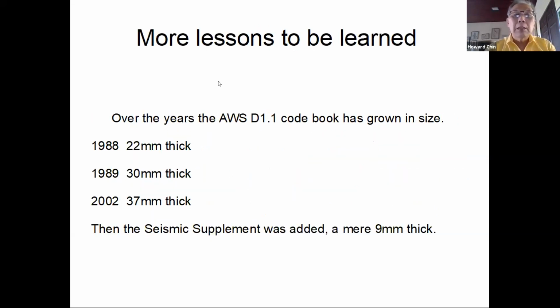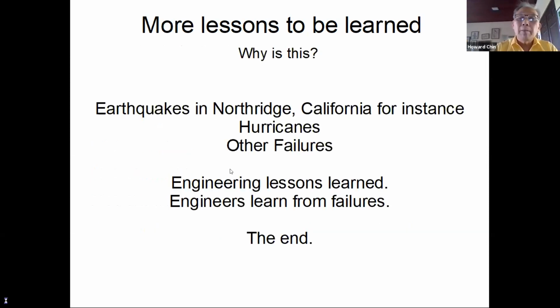Now, the lessons to be learned from this are that over the years, D1.1 has grown physically in size. In 1988, it was 22 millimeters thick. 1989, 30 millimeters thick. And getting closer to the current day, 37 millimeters thick. And then you add on a mere 9 millimeters of seismic supplement. Now, why is this? Earthquakes such as Northridge in California, hurricanes, and other problems that we've had cause changes in the building code.